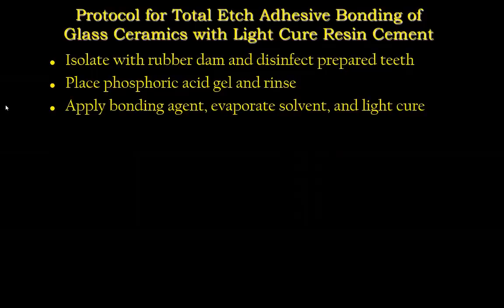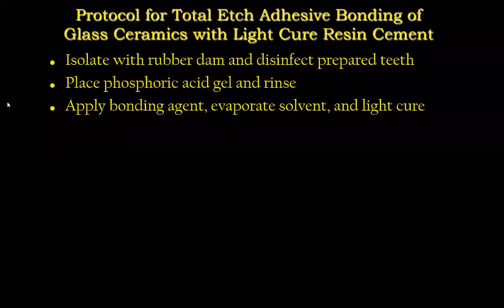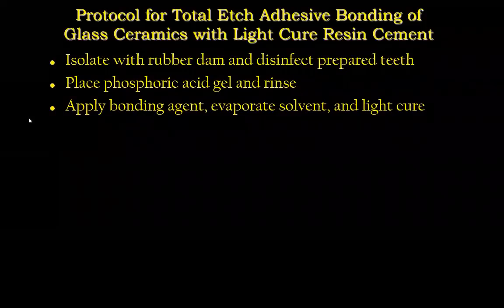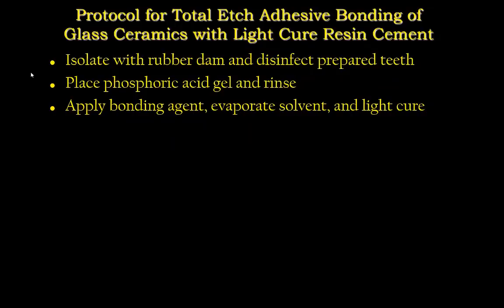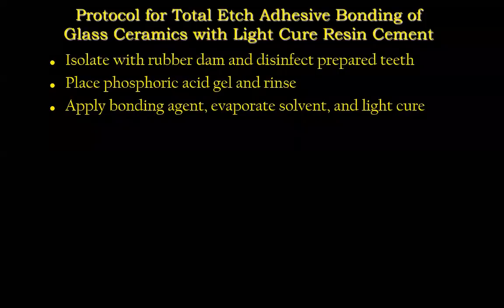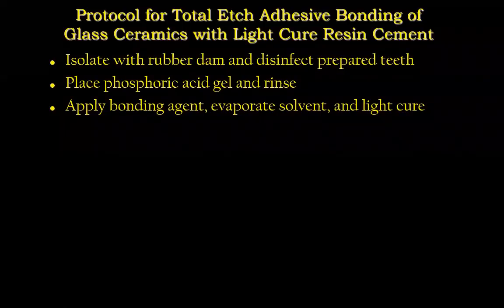We apply our bonding agent. In my case, it's going to be universal adhesive. I'm going to evaporate the solvent lightly by blowing air lightly until nothing moves, and then I'm going to light cure. I failed to mention this earlier, but this is critical. I don't care whose universal adhesive you use. For universal adhesives to work, they go on hydrophilic, which is water loving, which is important when dentin is involved, but they become hydrophobic after they're light cured. So it's critical for the success of universal adhesives, before you bond to them or before you seat the restoration, that you light cure your universal adhesive.